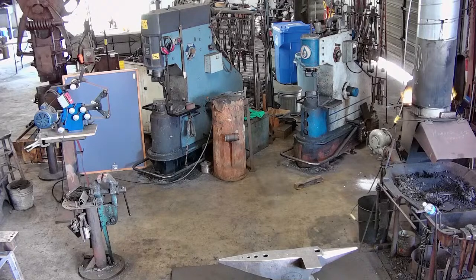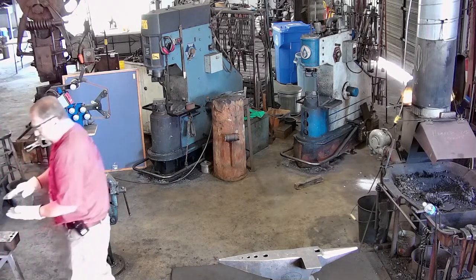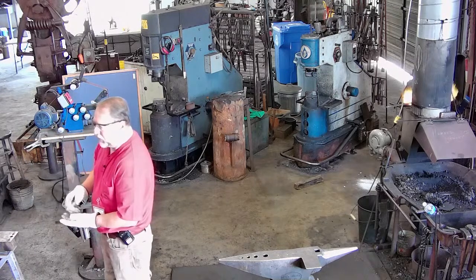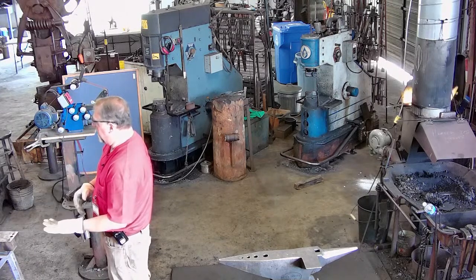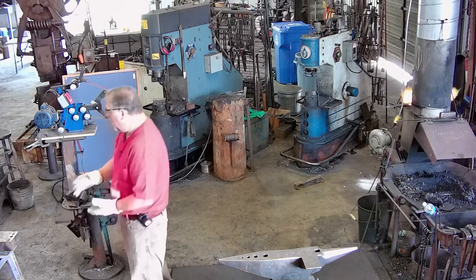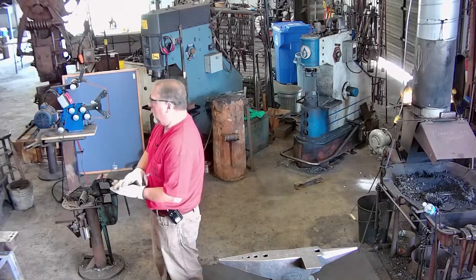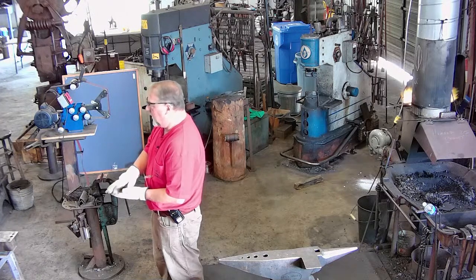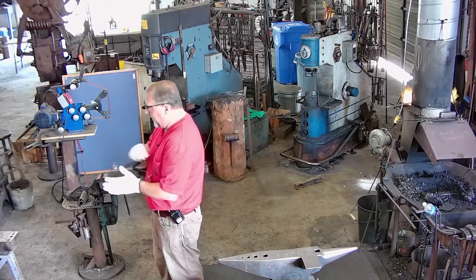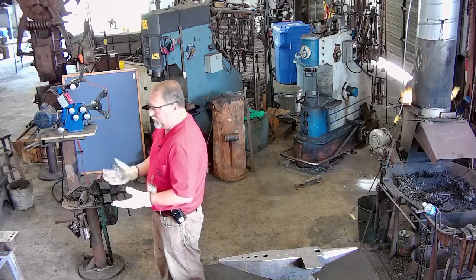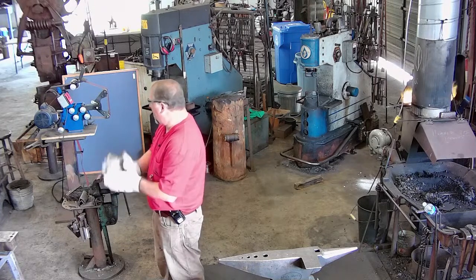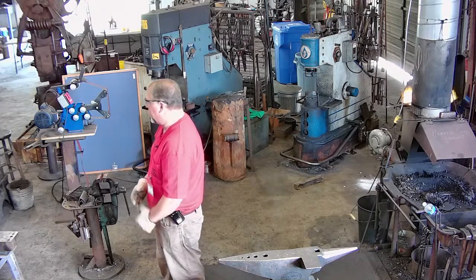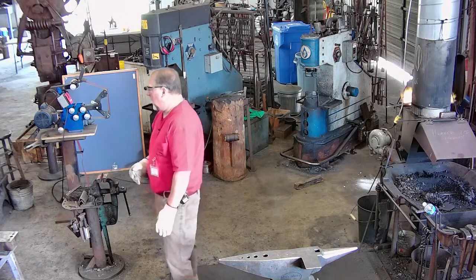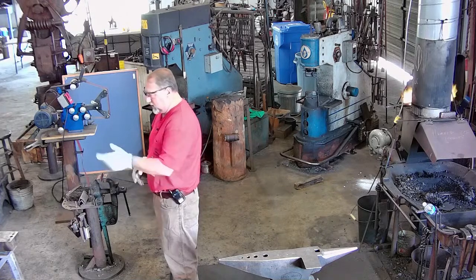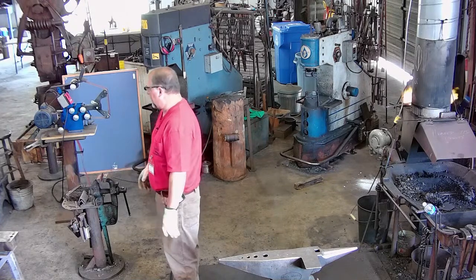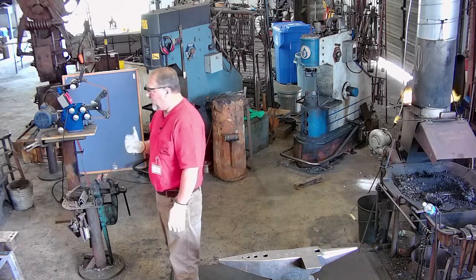So what we're doing, if you notice, the layers of steel are stacked and rotated: 1060, 15N20, 1060, 15N20. For this pattern, once I get a good forge weld in the entire billet, I turn it on its edge, and that becomes my flat from now on. If you picture taking a paperback book and squishing it sideways, that's what we're doing to get the horizontal lines in this billet. How many layers do you start with? 25 layers on this billet, and in the do-it-yourself kit, you get 25 layers. Do you have any questions before we get started hammering?